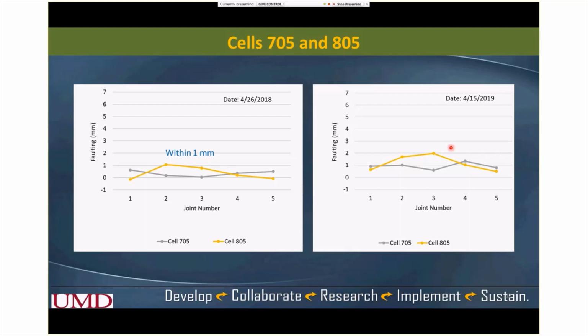705 and 805 also did not show a significant amount of faulting, but the load transfer efficiency and even the deflection values in these two cells were really high. The deflection was high, load transfer efficiency was very low, but we did not see faulting. My understanding, and there are a lot of experts in this room today, so we can think about it, is that the excessive deflection or poor load transfer we are getting in these two cells is probably due to the geosynthetic fabric that we used.